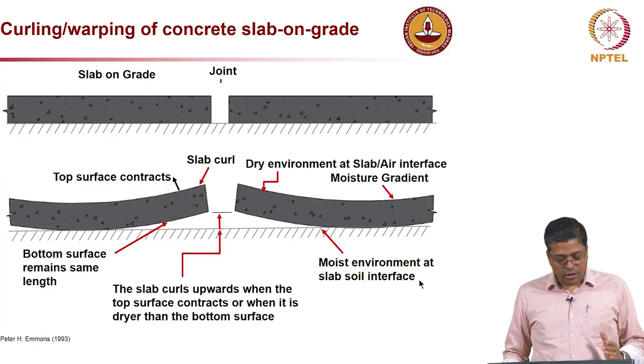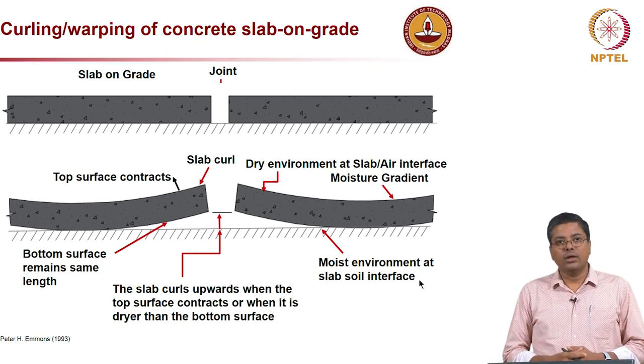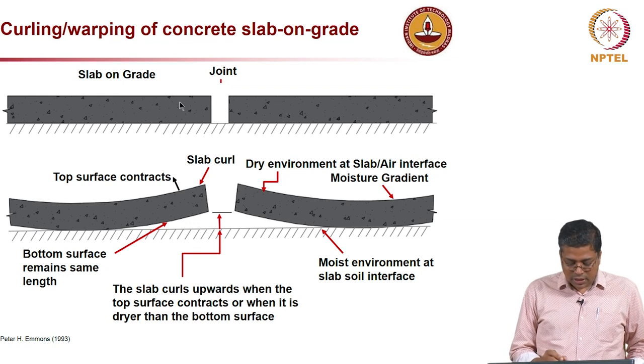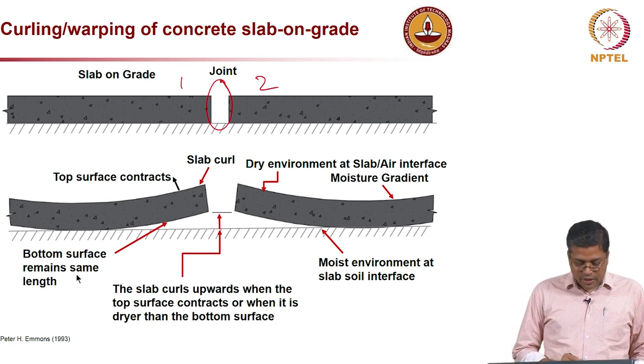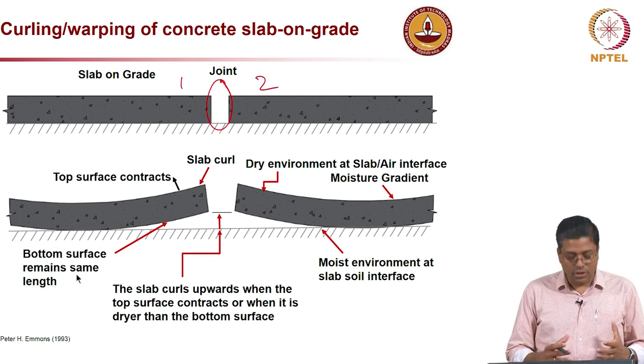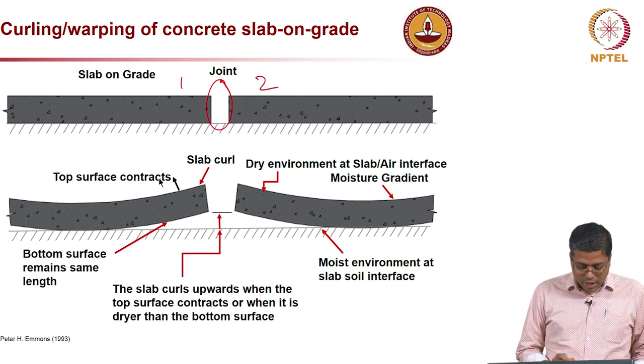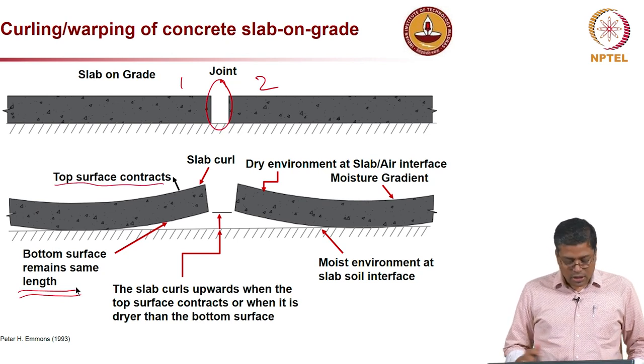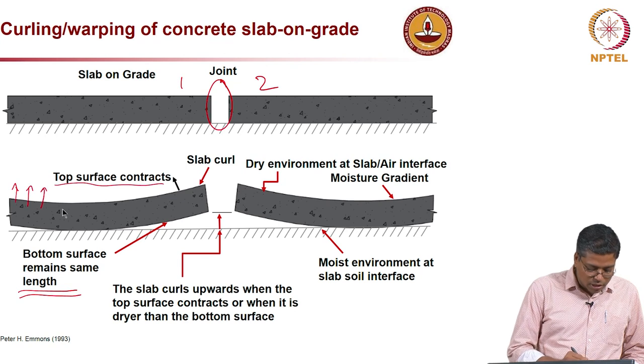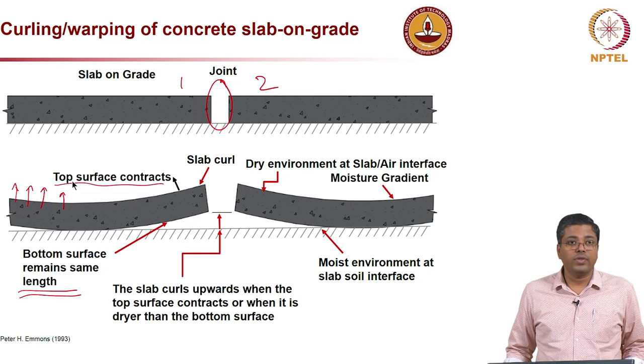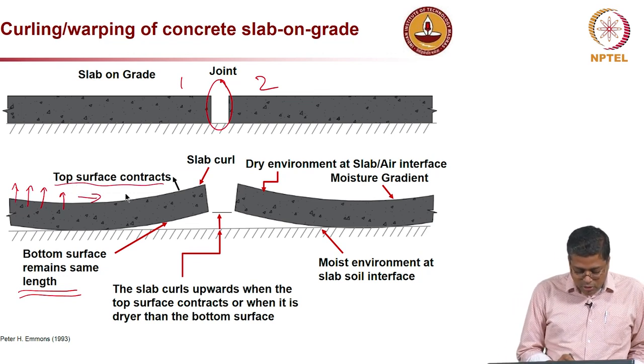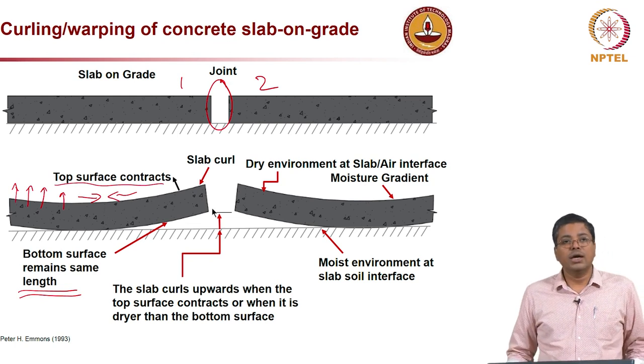Now this is an example showing how curling or warping of a concrete slab on grade happens, like a concrete highway or a concrete pavement. You can see here 2 slabs, 1 and 2, and there is a joint at the center. What will happen in a dry environment is that the top surface will try to contract, whereas the bottom surface remains at the same length. The moisture from the concrete is getting out, which leads to drying and shrinking of the concrete. Shrinking means the top is going to contract, whereas the bottom portion is at a similar length.